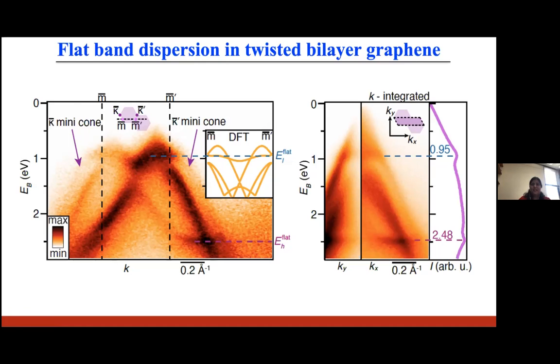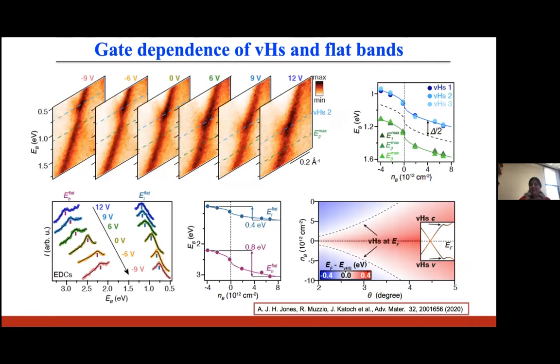So next, let us look at how the flat bands and these Van Hove singularities shift with the gate voltage. And so here is the ARPES spectra along the K points of the bottom and the top graphene Dirac cones. And you can see the Van Hove singularity shifts to a lower binding energy as we hole dope our sample by applying a negative gate voltage. And we can track this better if I plot them here